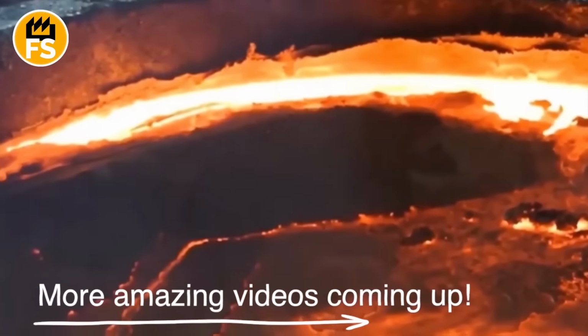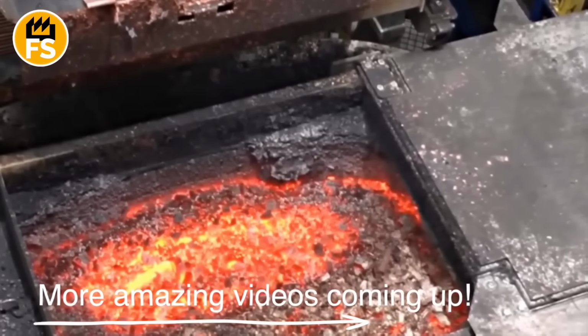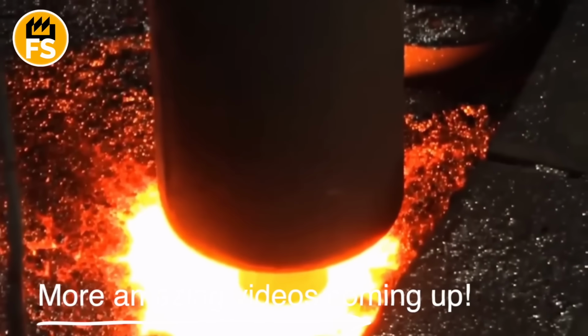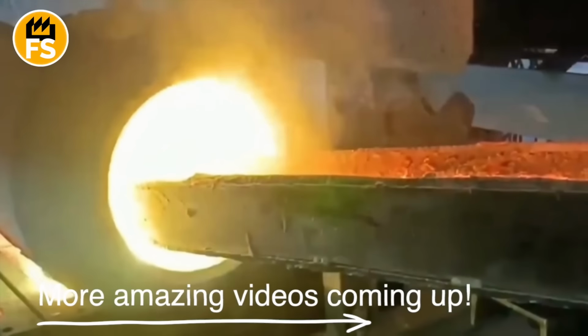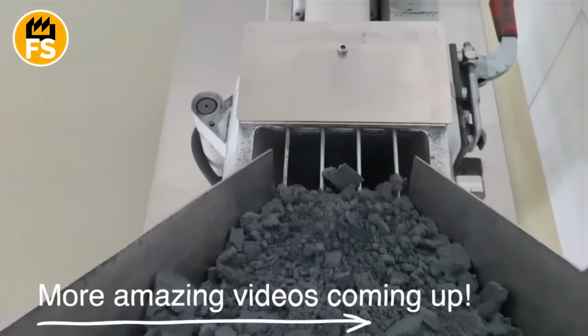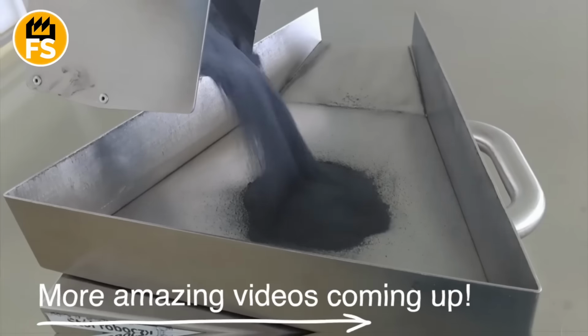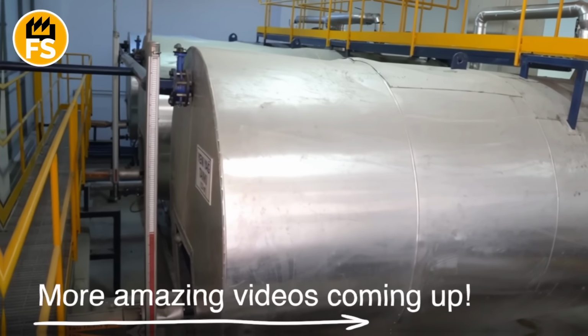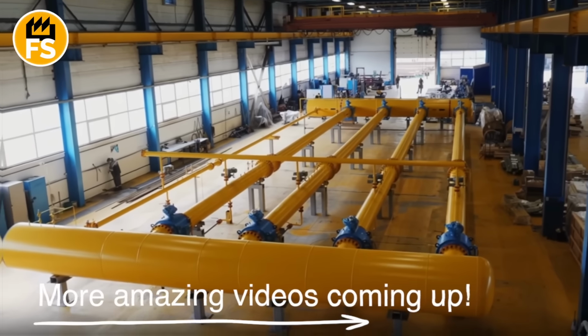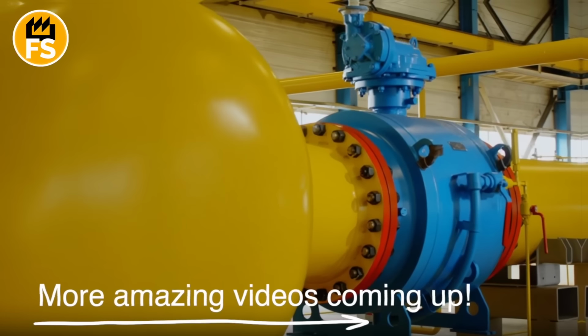The molybdenum concentrate gets roasted in special furnaces at temperatures around 2000 degrees Fahrenheit or higher in air. Molybdenum oxidizes to molybdenum trioxide, which can then be reduced to metal. But rhenium behaves differently. It oxidizes to rhenium heptoxide, which at this temperature evaporates and escapes with the gases.